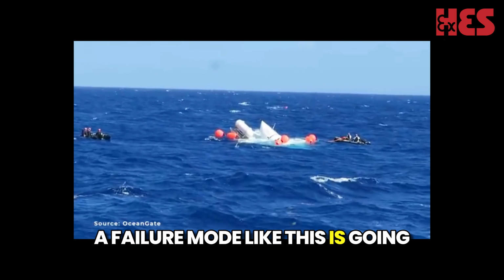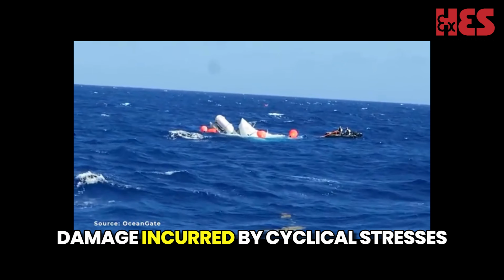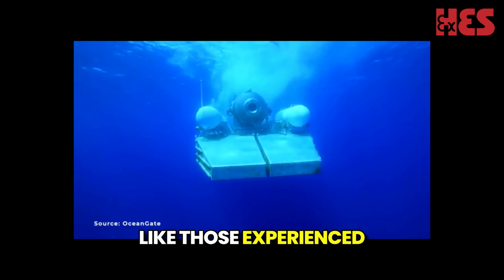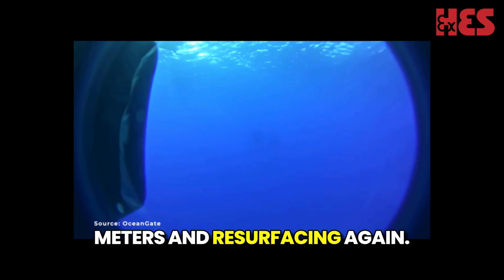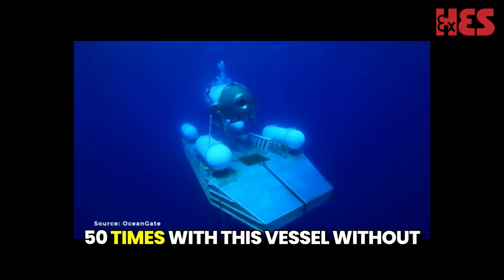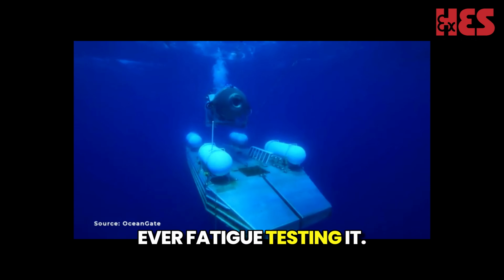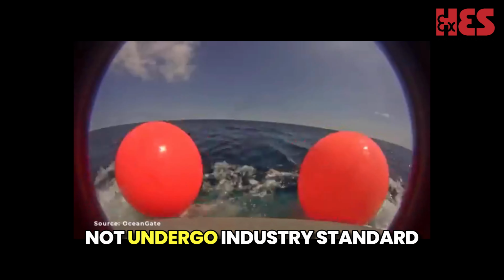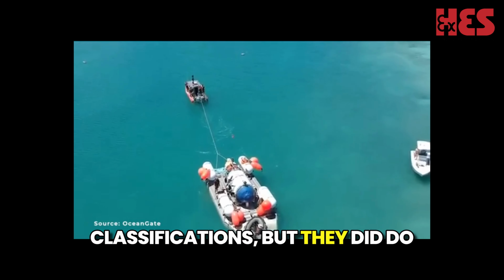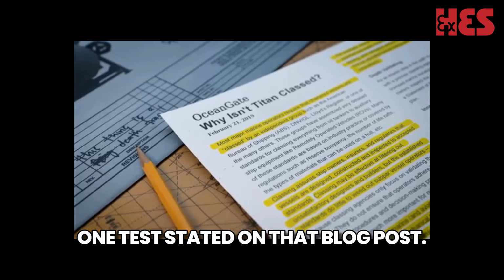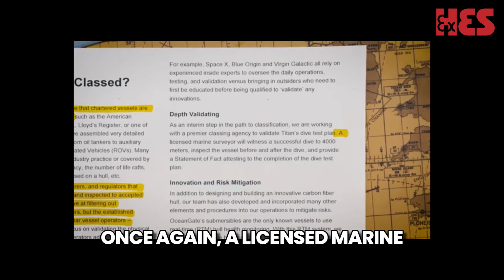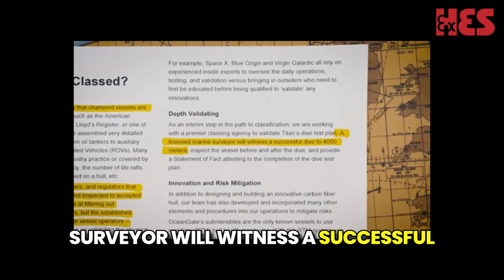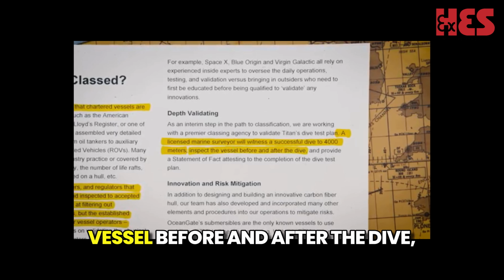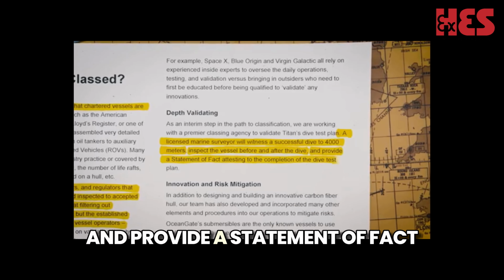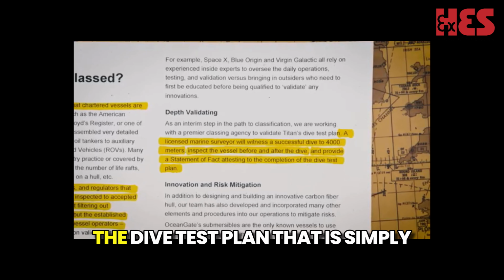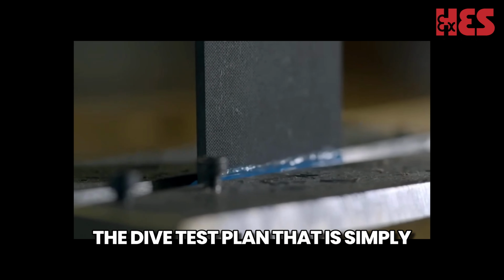A failure mode like this is going to be exacerbated by gradual damage incurred by cyclical stresses, like those experienced when diving to depths of 4,000 meters and resurfacing again. They have done that at least 50 times with this vessel, without ever fatigue testing it. Per their own admission, they did not undergo industry standard classifications, but they did do their own classification test. One test, stated on that blog post once again. A licensed marine surveyor will witness a successful dive to 4,000 meters, inspect the vessel before and after the dive, and provide a statement of fact attesting to the completion of the dive test plan. That is simply not adequate.